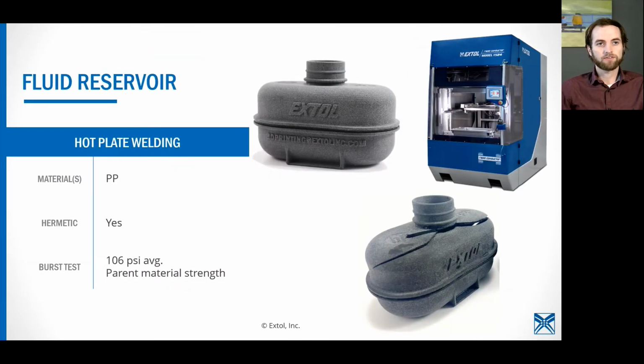This hot plate welding example is a polypropylene fluid reservoir as shown in the multi-jet fusion process video at the beginning of the webinar. It was welded on Extol's Rapid Conduction, which is a hot plate welder, and the weld joint is airtight, so it's a hermetic seal. And there's also parent material strength in burst testing, so that means it cracks away from the weld. This is what we like to see in both molded and printed parts.